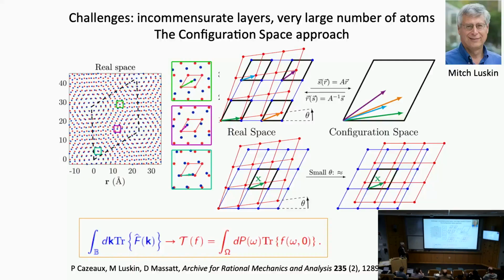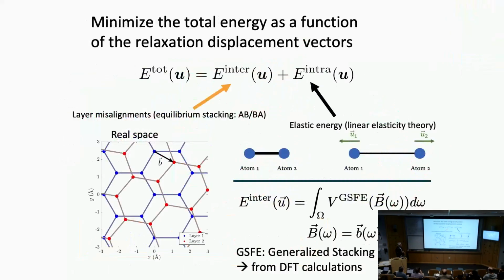So this is basically what we have done, but this implies that we need a Hamiltonian of finite range, because that's all it takes to describe all these local environments. With this type of Hamiltonian, which I'll mention in a second how we get, we can minimize the energy as a functional of all the atomic positions. There are two contributions, one from interlayer interactions and one from intralayer interactions. This comes from linear elasticity theory, which is good enough to capture all the energy changes due to change in position of atoms within the layer.